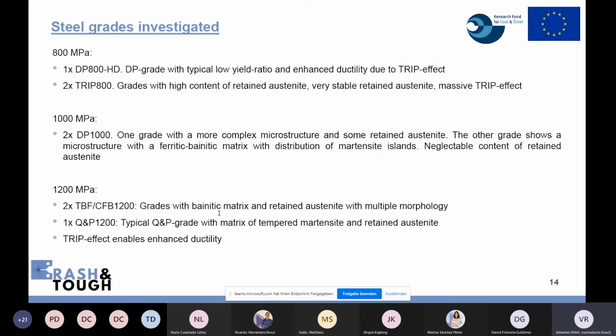Finally, I would like to summarize the most important information about the steel grades. Well, as I said, we had 3 strength classes. In the strength class 800 megapascal, we had 1 DP800 high ductility, that means a DP grade. This is a typical DP grade with a low yield ratio and enhanced ductility due to a TRIP effect from the retained austenite. Then we had 2 TRIP steels with very high content of retained austenite and very stable retained austenite and massive TRIP effect.